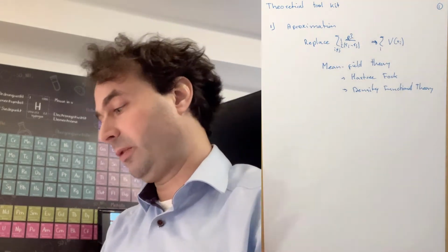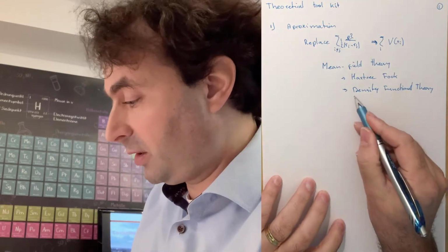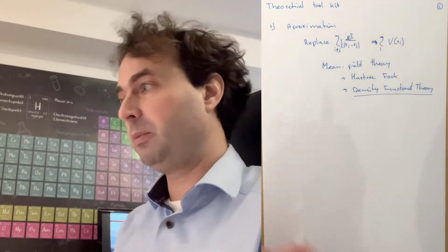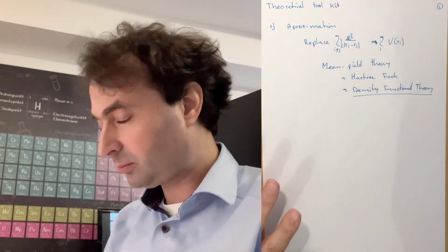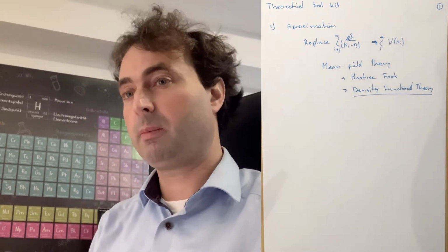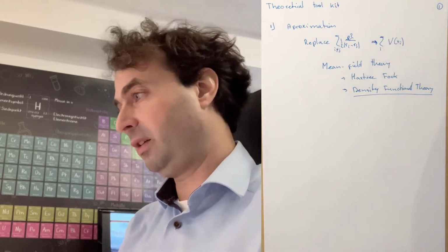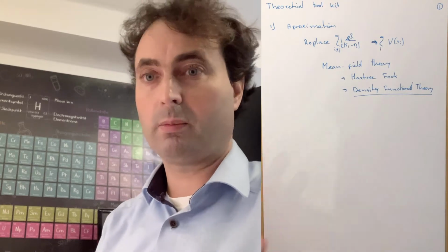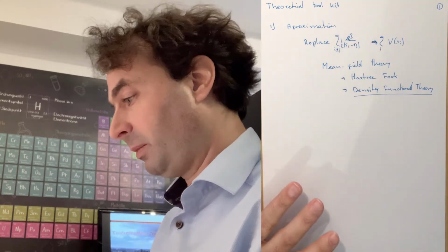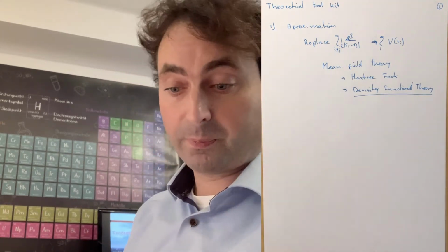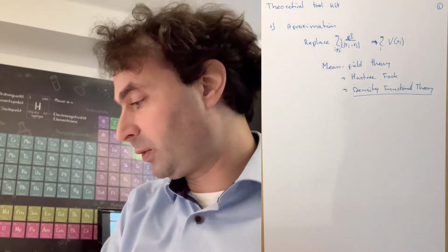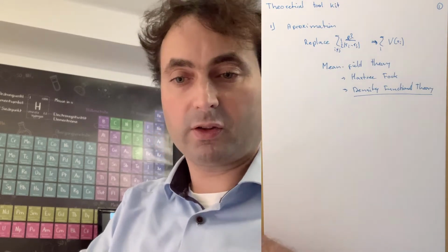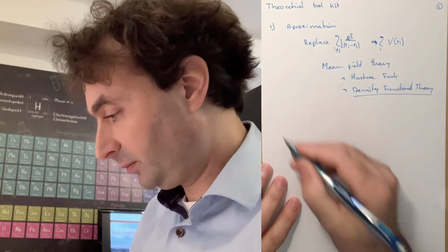It is still one of the most successful approximations that we have. And it is this method that works for about 1/3 of the materials, which you can use to describe your semiconductor electronics or titanium or aluminum. But it's also going to fail on magnetism or correlated systems, transition metals, superconductivity, and many more. So it works for about 1/3 of your materials. Not bad, but not something to be fully satisfied with.